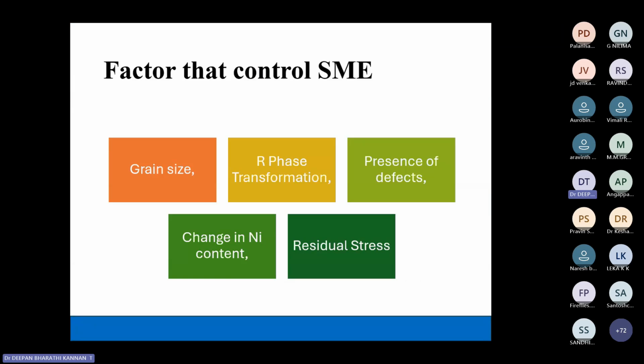If the phase transformation temperature is affected, obviously the shape memory effect will also be affected. So in case we are planning to control the shape memory effect, we need to fine tune the grain size, minimize this R phase transformation, and do the wire cutting manufacturing in such a way that there are no defects like pores, cracks, and other inclusions because of improper shielding. And we need to make sure that the nickel content does not change. And then residual stress, obviously, because of the uneven heating and cooling, will result in residual stress. So that also has to be minimized if you are focusing on shape memory effect.